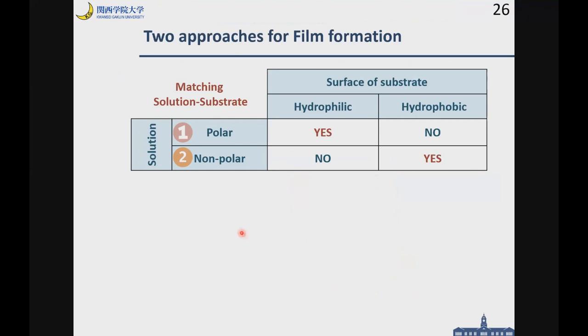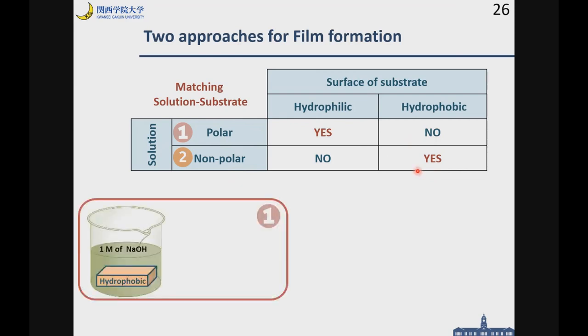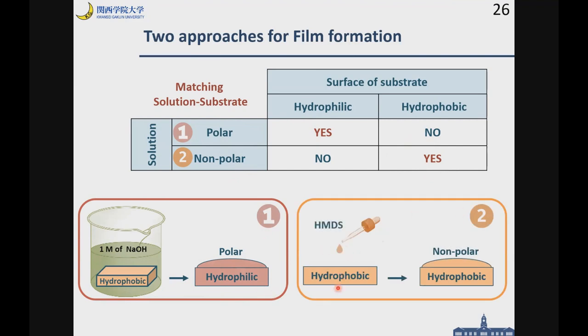Okay, two types of matching. One is polar solution or polar solvent on the hydrophilic substrate, and the other is non-polar solution on the hydrophobic substrate. We can control the surface characteristics, hydrophobicity and hydrophilicity. When we treat the substrate with NaOH, we can make a hydrophilic surface. On the other hand, when we treat it with HMDS, the surface becomes hydrophobic. Therefore, we can control the surface characteristics.